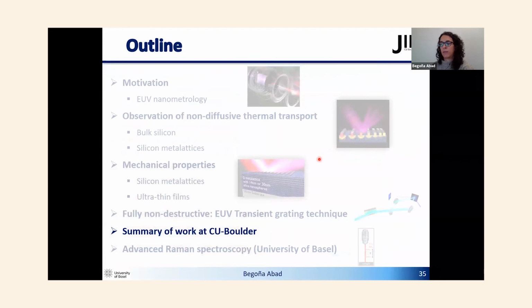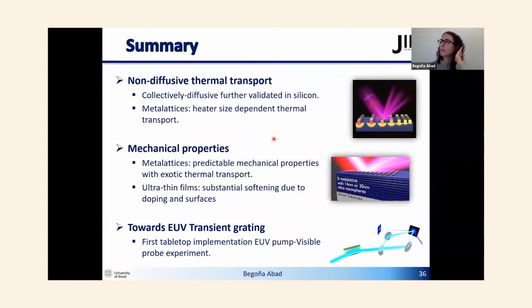Okay, now the summary of the work at CU Boulder. From the non-diffusive thermal transport point of view, we were able to validate the collectively diffusive regime in silicon, and also in the metalattices, we saw how the heater size affects the thermal transport, that there is a dependency, even though it is not predicted from the macroscopic point of view. So this also proves that there is non-diffusive thermal transport.